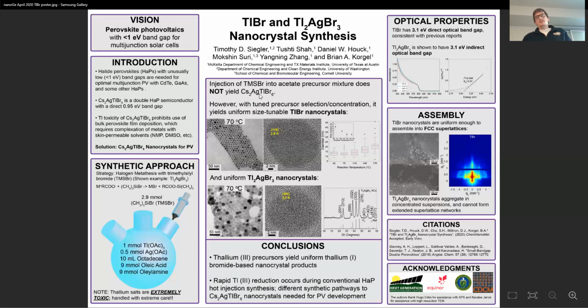While we did not yield the desired cesium silver thallium bromide nanocrystals we were looking for, by taking the cesium and silver away, we were able to yield very nice, well-dispersed, shape and size uniform thallium bromide nanocrystals, and synthesize, for the first time anybody has done this, thallium silver bromide nanocrystals of double perovskite type crystal structure by adding the silver back into the precursor solution.